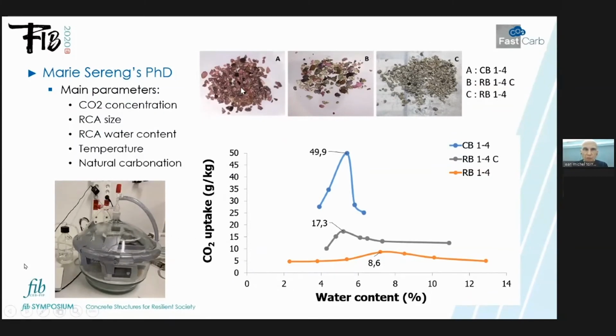For instance, we sprayed phenolphthalein on the aggregates. You could see that here they are not carbonated, while here they are already carbonated. And there is, of course, a big difference between this one and this one. So you see, of course, the importance of the natural carbonation on the uptake we can obtain by accelerated carbonation.